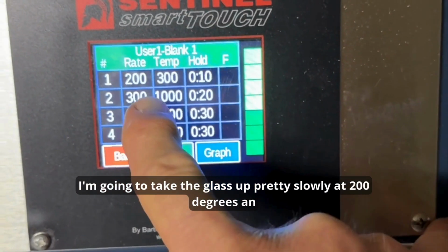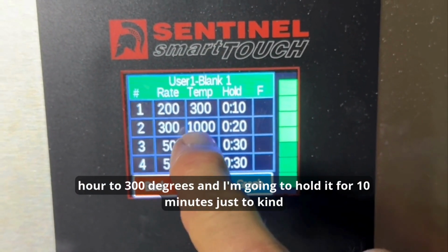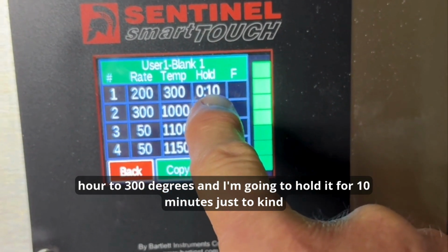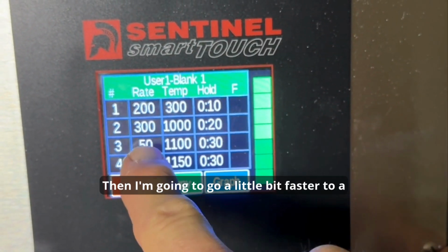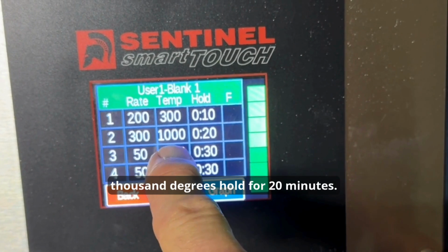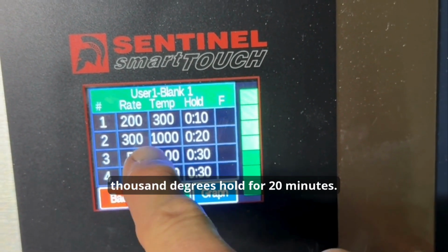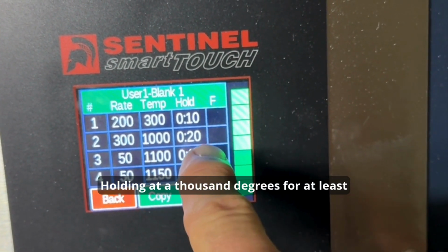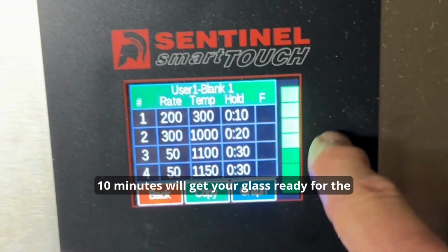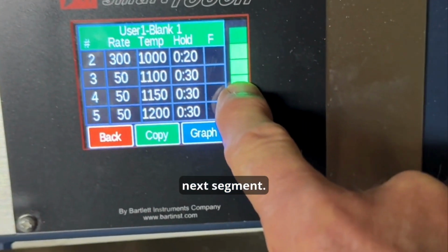and then I'll take it to the full fuse. I'm going to take the glass up pretty slowly at 200 degrees an hour to 300 degrees, and I'm going to hold it for 10 minutes just to kind of get everything warmed up. Then I'm going to go a little bit faster to 1,000 degrees, hold for 20 minutes. Holding at 1,000 degrees for at least 10 minutes will get your glass ready for the next segment.